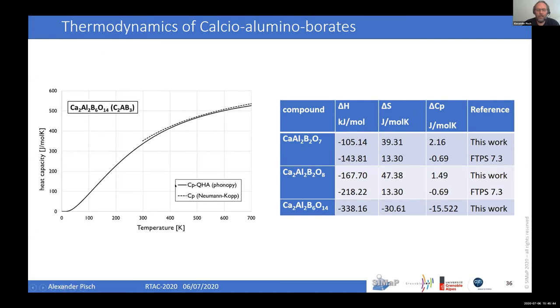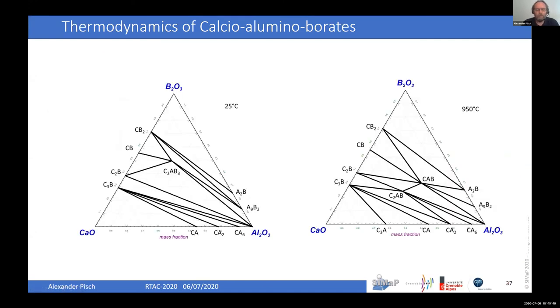So if you produce now Gibbs energies out of these data and try to calculate, you see that this compound, supposed to be stable only at high pressure, is stable at 25 degrees Celsius. And if you calculate then, it decomposes at, let's say, around 400 to 450 degrees Celsius. At that high temperature, you really find what is known from the literature. So it's clear that the so-called high pressure only compound does exist at room temperature, so at low temperature. So it's really a stable phase under normal conditions.